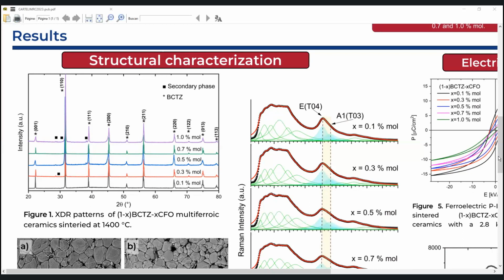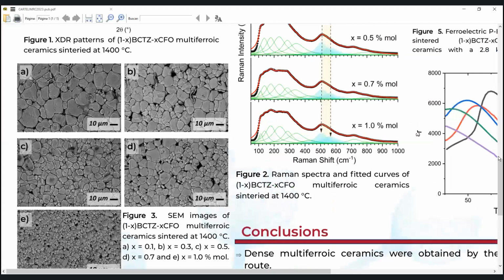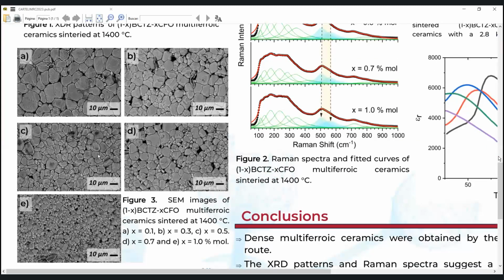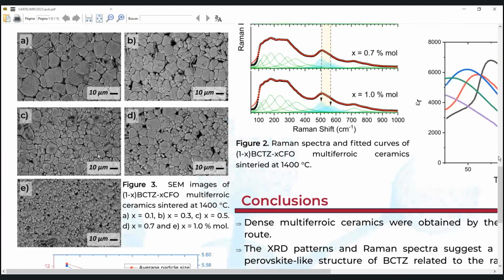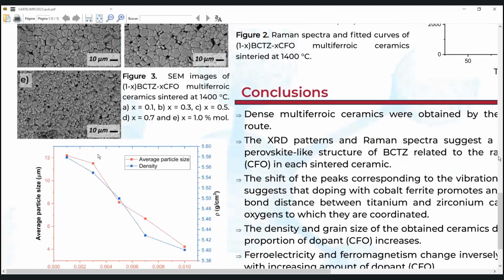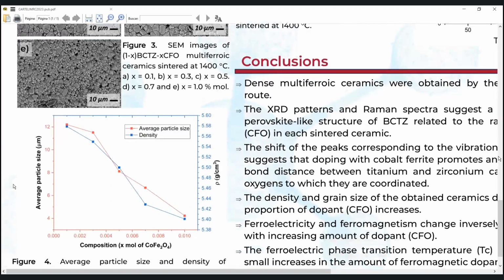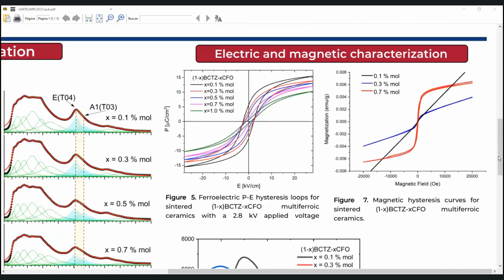The scanning electron microscopy results show a gradual decrease in the density and particle size of the ceramics as the proportion of dopant increases. Again, this may be due to microstructural stresses or structural deformation, closely related to the increase in dopant concentration. On the other hand, electrical and magnetic analysis were carried out on the samples.